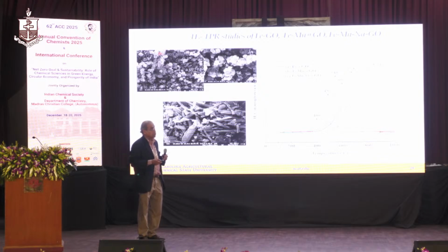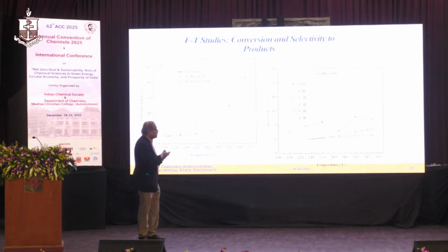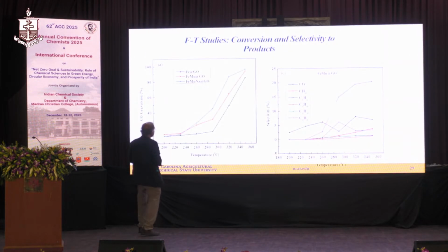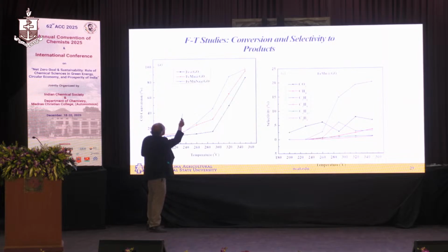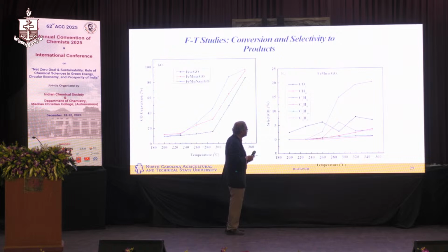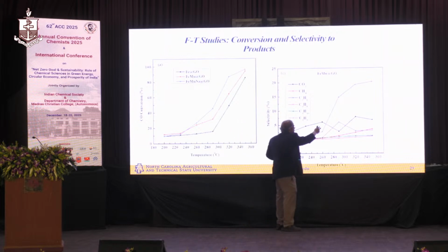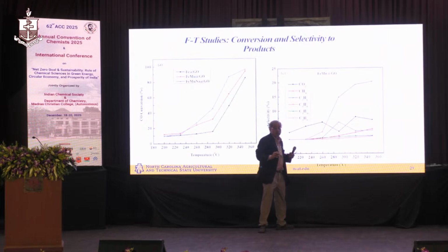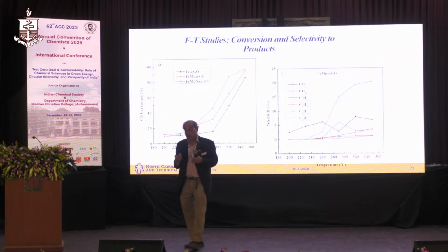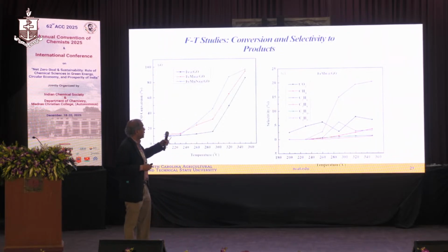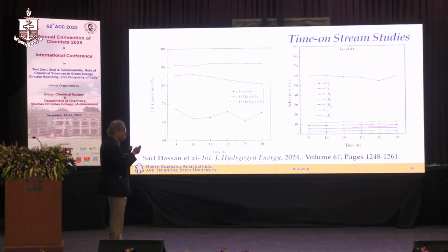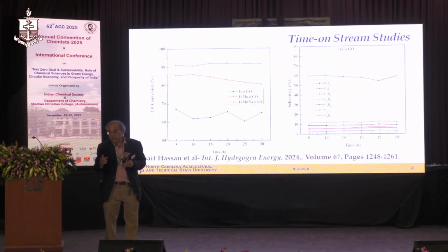There's another thing that one can look at, the morphology of the catalyst. Okay? So once you do that, then you try to do the reactions, and what he found with the addition of the promoters, manganese and sodium, is that the CO conversion goes way up, above 90%. So this is really, really high. And then if you look at the selectivity of the products, you can see the propene, C3H6. See that this goes up. So we were very happy that we could generate the olefin, because this is proof of the concept, right? And so we got this, and in the interest of time, I'll just go through this quickly. And again, you do the stability.